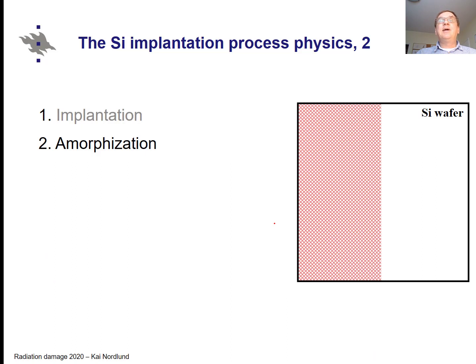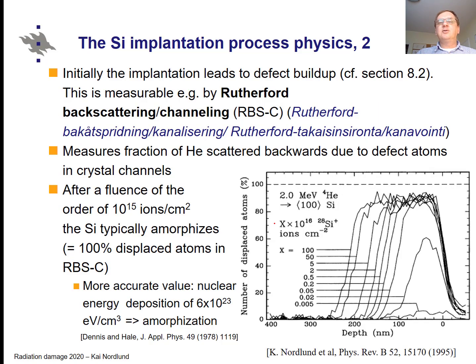But this is only the beginning, and it's actually much more complicated physically. After implantation you reach the high-dose effect and you amorphize silicon. This can be measured with a method called Rutherford backscattering channeling, where you basically measure how much helium is backscattered due to defect atoms in crystal channels. Many experiments — this one from our own lab is just an example — show that after a certain irradiation dose you get highly disordered material which is at or close to the so-called amorphous level.